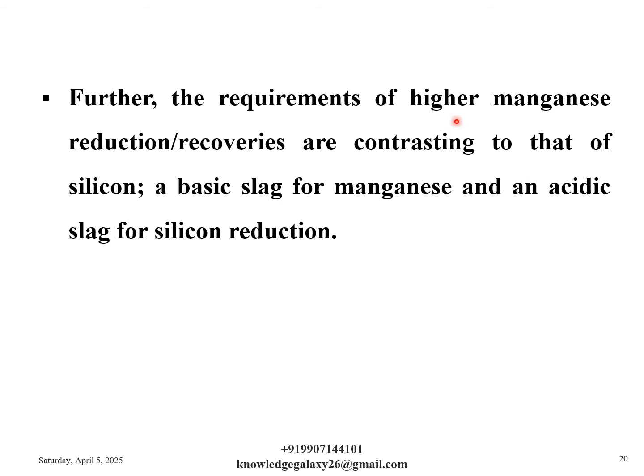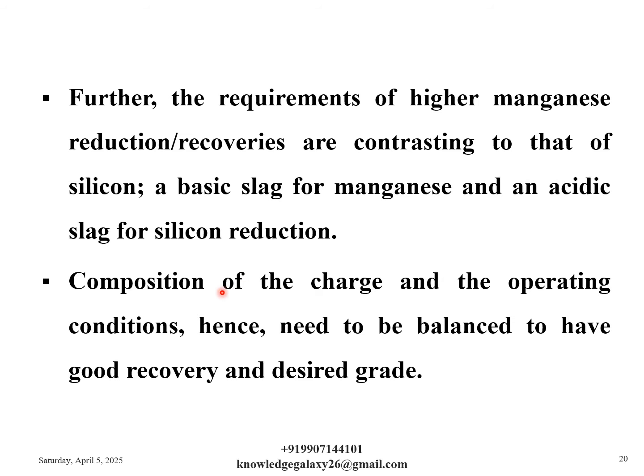Further, the requirements of higher manganese reduction or recoveries are contrasting to that of silicon, that is, a basic slag is required for manganese reduction and an acidic slag for silicon reduction. Composition of the charge and the operating conditions hence need to be balanced to have good recovery and desired grade.